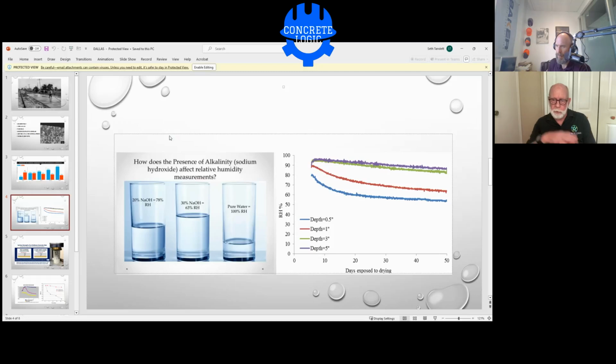because I was under the assumption, as everybody else is, that the moisture content of the concrete is fairly consistent and remains above 80%, because 80% will form cement. Once the relative humidity drops below 80%, cement formation will not occur. It will just stop. Now, that explains the weak porous surface. But they're not tying that in with the alkalinity, which is really unfortunate. And I don't know why, but they're not.